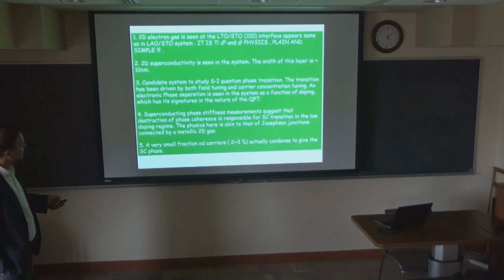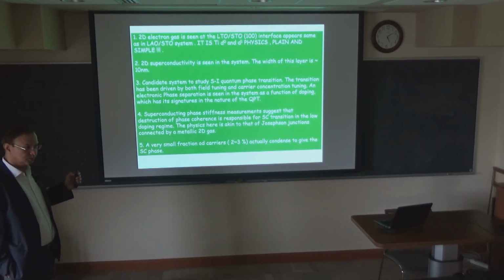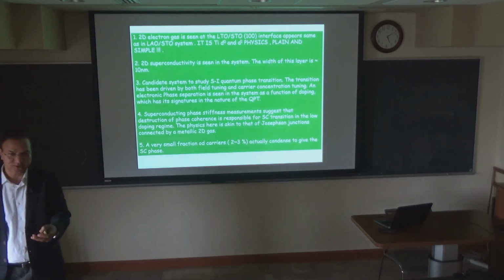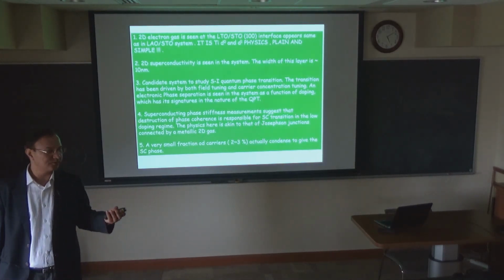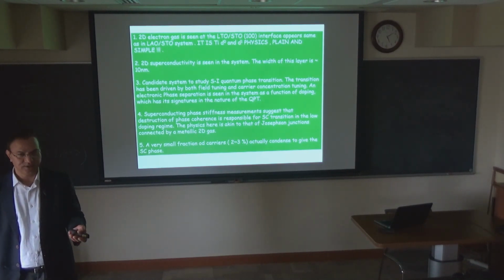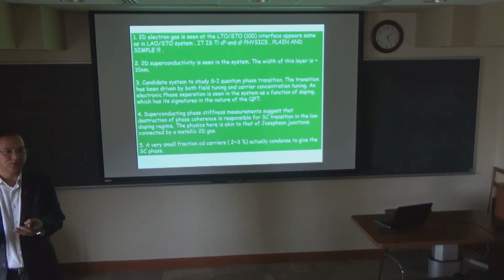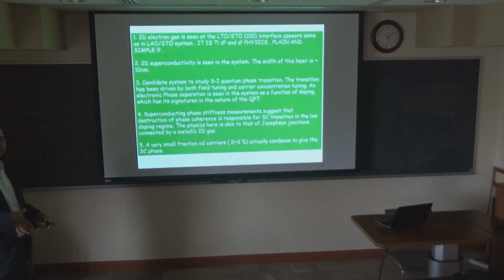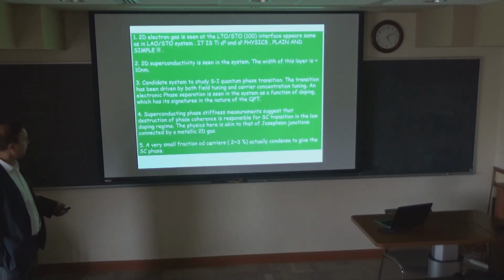Superconducting phase stiffness measurements suggest that destruction of phase coherence is responsible for the superconducting transition. That's the latest microwave data in the low doping regime. In the low doping regime, you have the possibility of uncorrelated Cooper pairs existing above the transition. And only when you have robust phase coherence do you see bulk superconductivity in the underdoped regime. In the overdoped regime, everything is normal. So this phase transition in the underdoped regime is akin to that of Josephson junctions connected by a metallic two-dimensional gas.